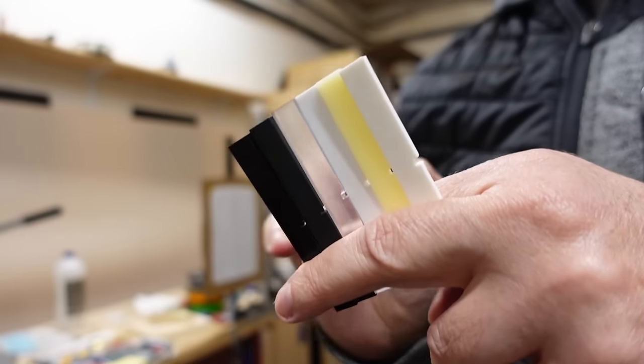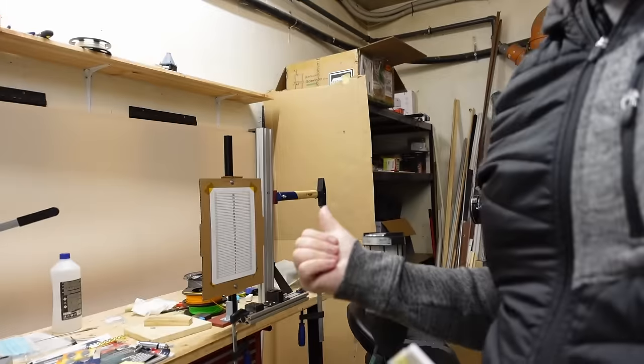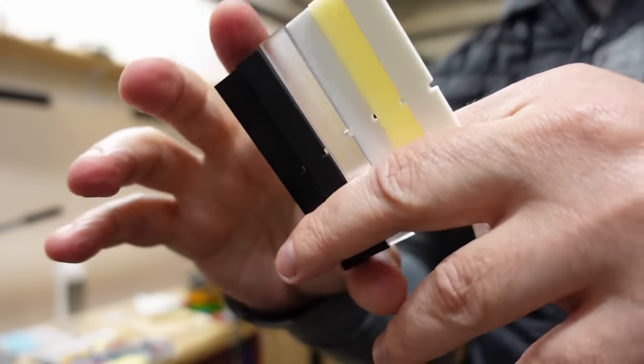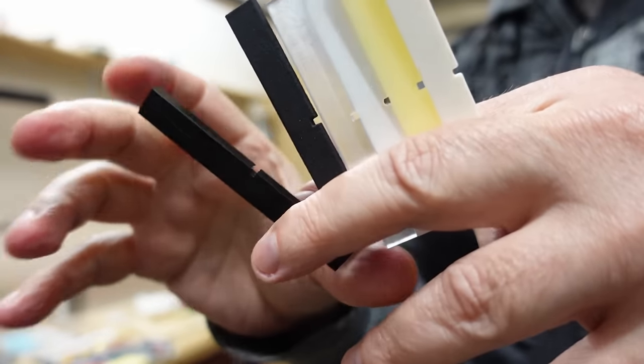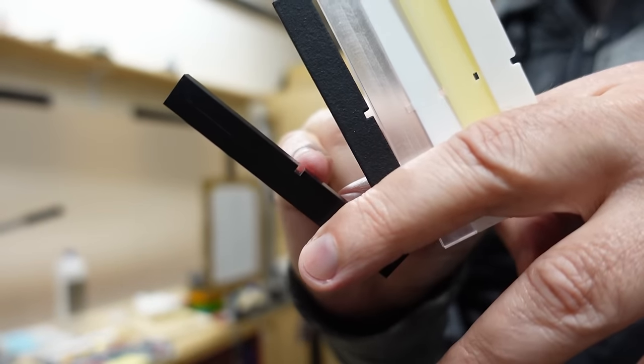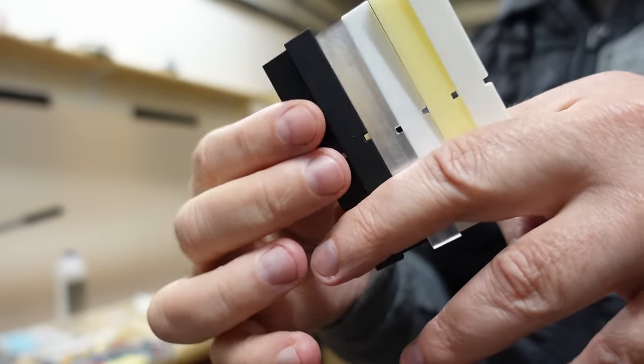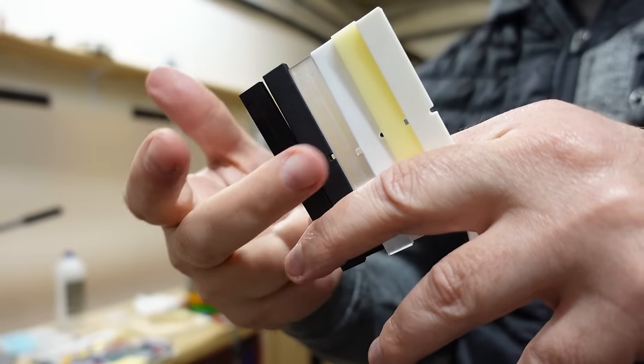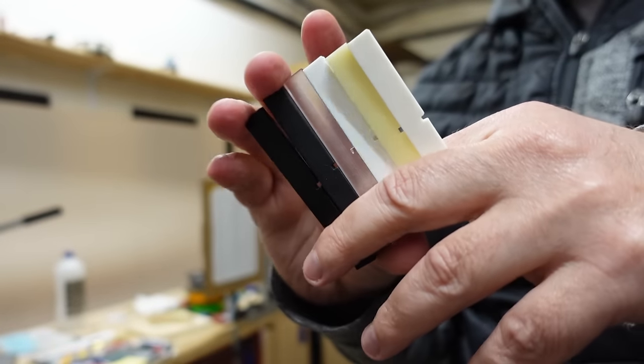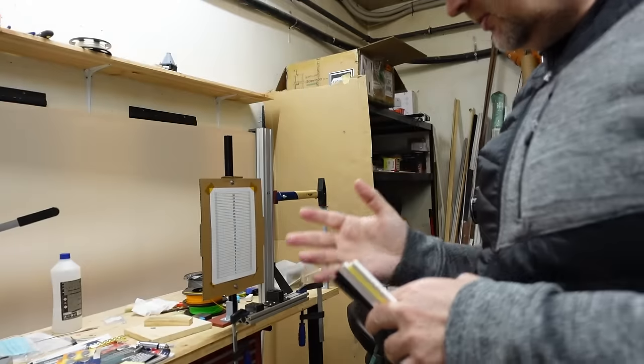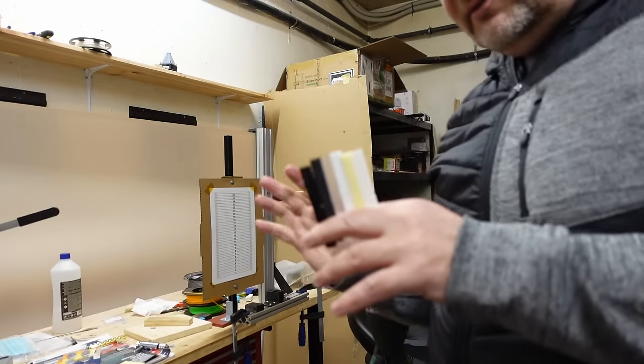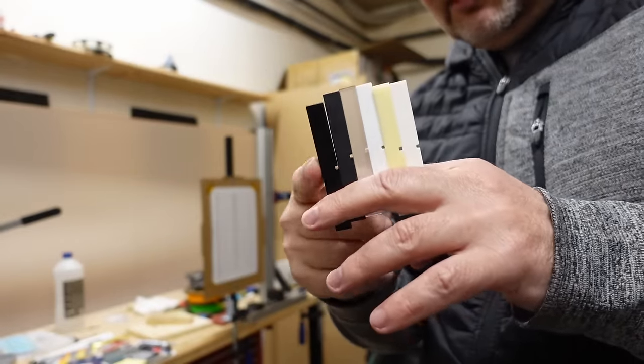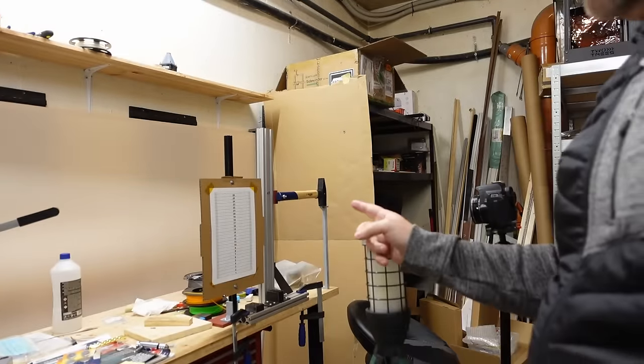And now the IZOD impact test with this 1.5kg hammer. And these are not original IZOD test objects, because here I have a 2x2mm slot, because I want them to be equal on 3D printed and CNC machine parts. And I'm not really sure, but I have the feeling that some of these test objects will not even break under this 1.5kg hammer.